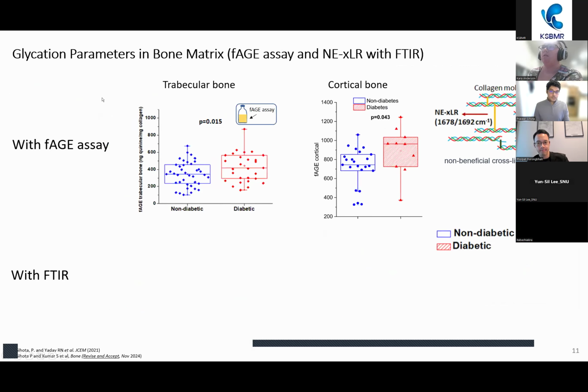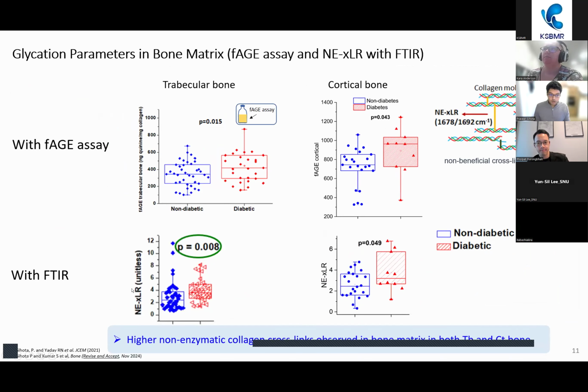Then, of course, in type 2 diabetes, glycation in bone matrix is also important. So for that, we did glycation quantification in two ways. One is the FAGE assay, that is fluorescent advanced glycation end product. So basically the advanced product which makes cross-linking with collagen matrix has been studied. And we found FAGE content is higher in the diabetes group for both trabecular and cortical bone, and non-enzymatic cross-link, which is studied with a spectroscopic technique, is also elevated in the diabetes group.